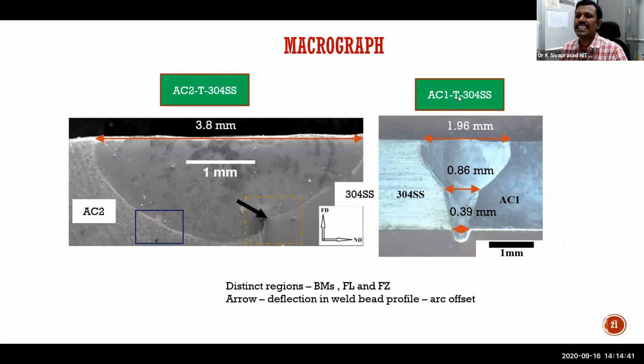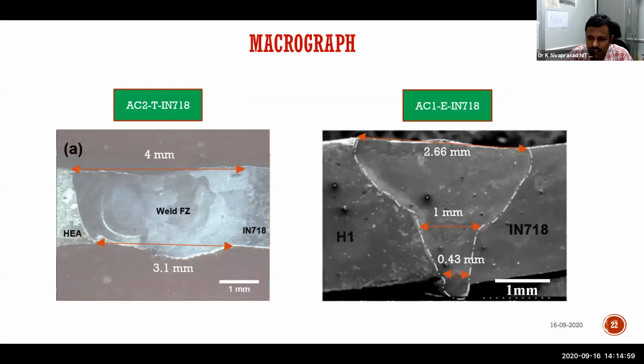Sorry, this is HEA to 304 stainless steel with the same thickness. Please understand the thicknesses are the same. We have seen a very wide 3.8 millimeter fusion joint in TIG welding, whereas 1.96 millimeter wide fusion joint in the case of electron beam weld. And when we have done the same thing with Inconel 718, slightly larger because the system demanded more fusion penetration, we have slightly increased the current, so it is slightly increased.